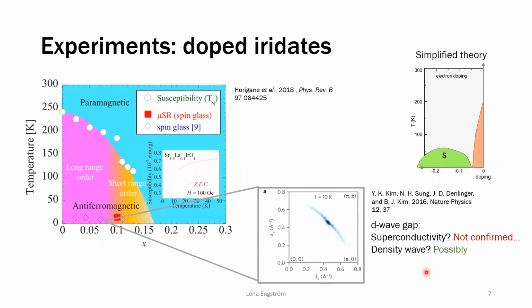So I guess for this in situ potassium doping experiment, it's still up in the air, right? It's still not clear from the experimental point of view what the underlying order is that's doing this, if any. Yeah, it's unclear. But whatever order it is, it's still interesting, right? To have these arcs and then this D-wave structure factor, it's non-trivial. It's correlated with a phase that appears, but the simple model doesn't seem to be good enough.